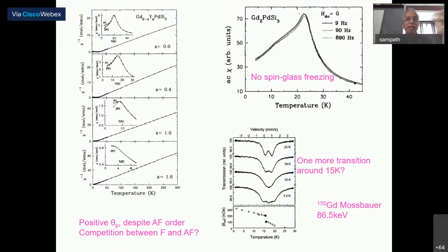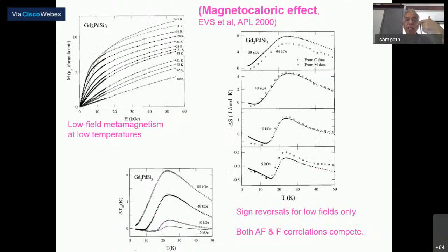As I already mentioned, the susceptibility data, AC and DC both, have shown there is a competition. You have both ferromagnetic and antiferromagnetic interaction here. However, there is no spin glass behavior. We raised the question, there is an interesting competition here in this material at that point of time. And if you look at the isothermal entropy change, derived from Maxwell's equation using the magnetic data, and also heat capacity, there are sign reversals in the delta S here, you could see, plus and minus. This also tells you there is both antiferro and ferromagnetic interaction across the material.